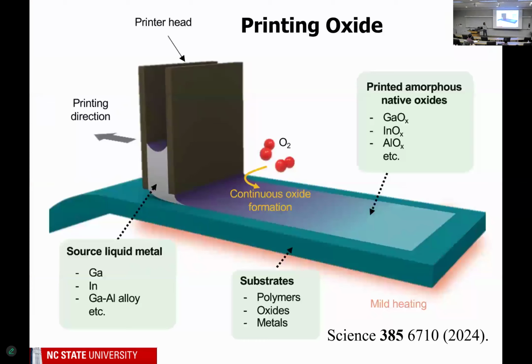Now, I know the box folding was cool and the vacuum filling was cool, but this is even more cool. It's just there's nothing to see. And that's what's so cool about it, is that the oxide that we're depositing is beautiful. There's no defects. It just completely covers this large area. And this is at room temperature. No vacuum processing, no high temperatures. We're depositing oxide. Now, there is a little bit of liquid residue at the edges, which we can't seem to quite avoid. But other than the edge, we're just depositing the oxide.